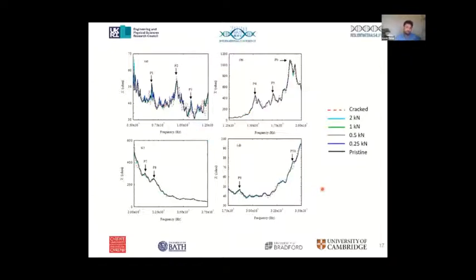Now, on the face of it, looking at these slides, there doesn't seem to be much difference occurring. The changes are very, very subtle. But actually, with some quite innovative analysis and computation, you can read quite a lot into these responses. And it's very clear you can see exactly when the concrete must have cracked, which would then be able to be logged and put into an algorithm to get this automatic healing.